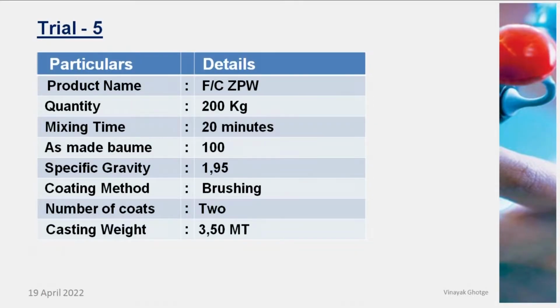The 4 trials photographs what I have showed you, it was aluminum silicate water-based coating. Now the trial which I am going to show you now, this is a zircon-based coating which is used on larger castings. This was a trial at one of the big foundries. The casting weight was about 3.5 tons. And the product was used by brushing application.